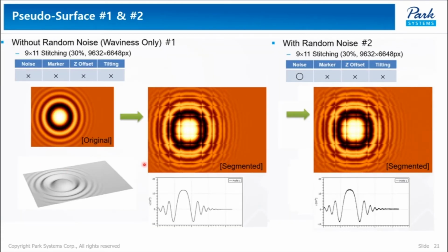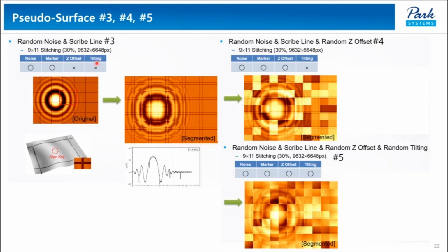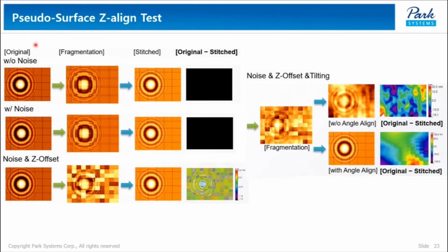These images are without and with noise, segmented 9 by 11, which means this image is constructed by 99 images stitched. Pseudo-surface number 3 includes scribe lines, number 4 includes random Z offset without tilting, and number 5 has random Z offset with tilting. These are results of the stitching algorithm. At this time, all images include scribe lines. Without noise, of course, there are no errors. Just including noise, no error was produced in stitching as well.